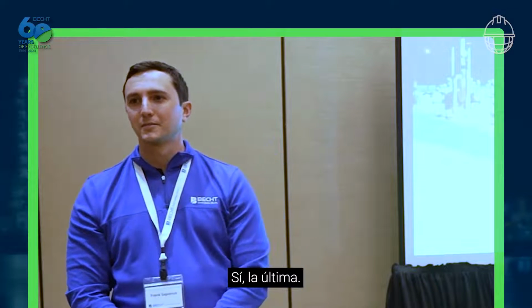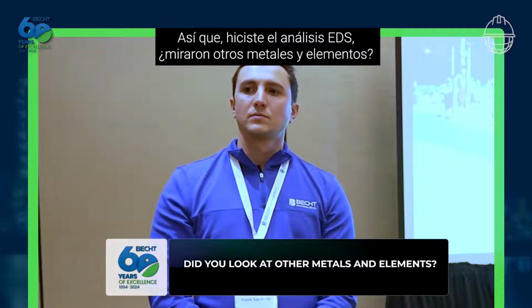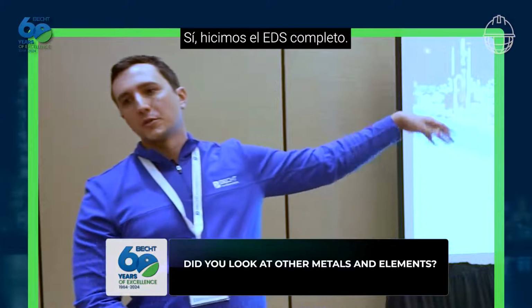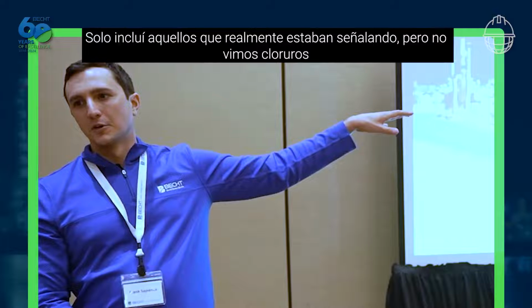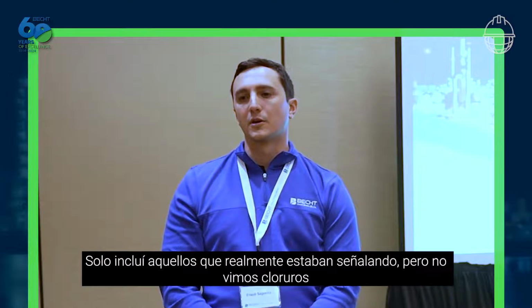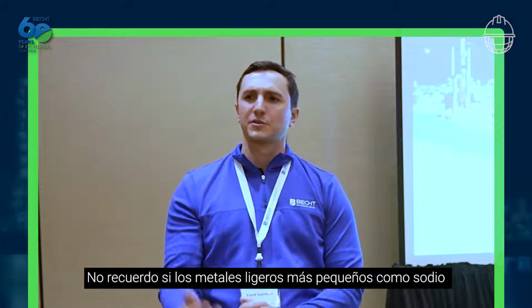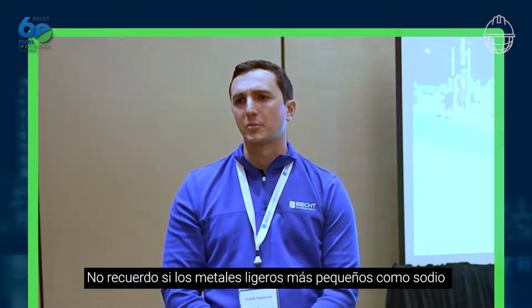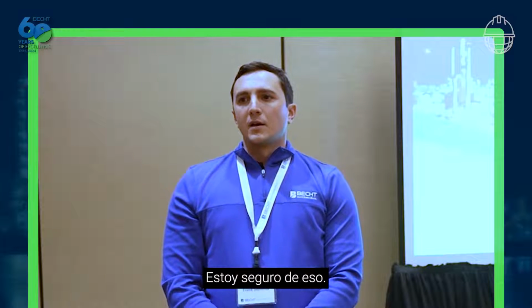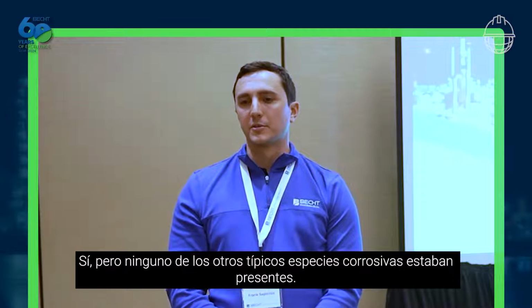Yeah. So in the last one, in your EDS analysis, did you look at any other metals, elements? Yeah, so we did do the full EDS. I just included those which were actually flagging, but that was where we didn't see any chlorides or other corrosive species. I don't recall if sodium or any of the smaller lighter metals were present in terms of things like that. But nothing. None of the other typical corrosive species were present.